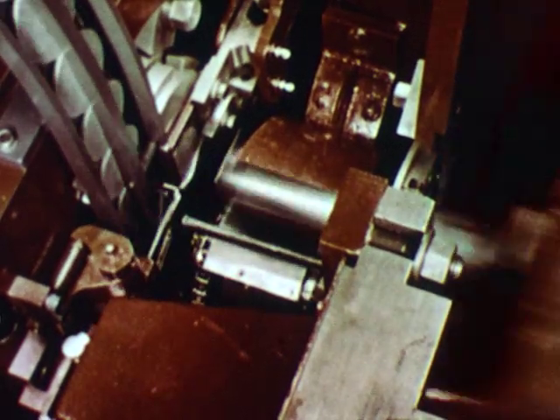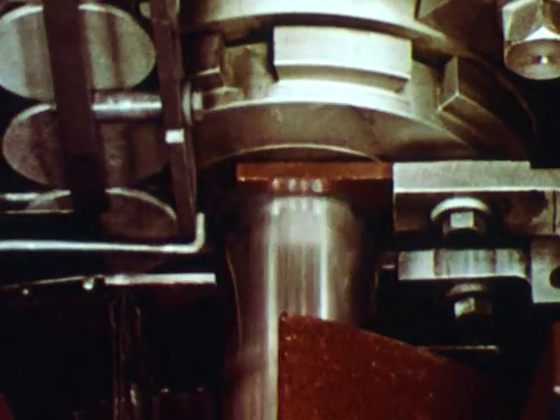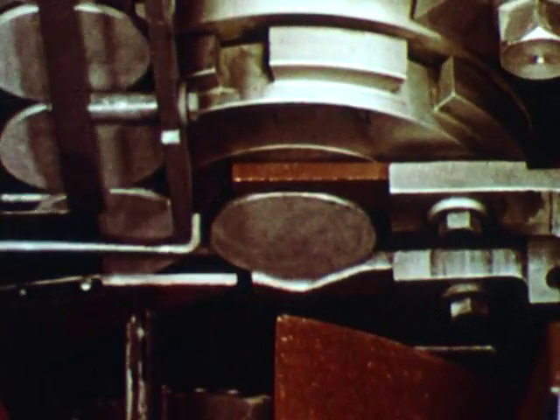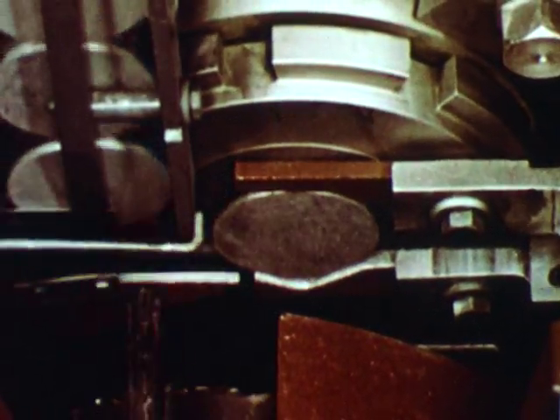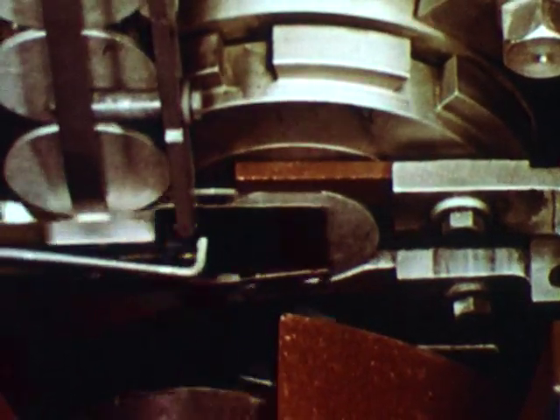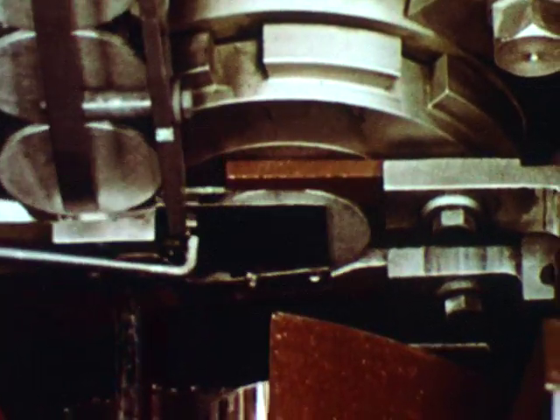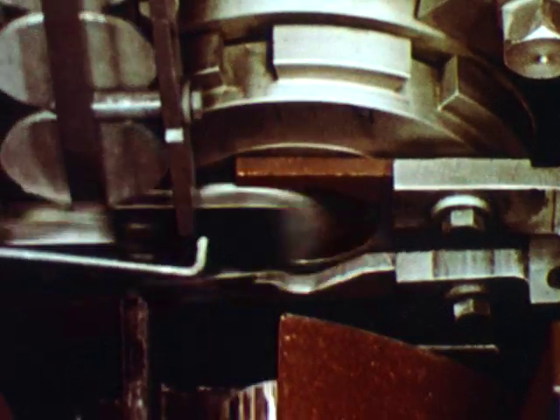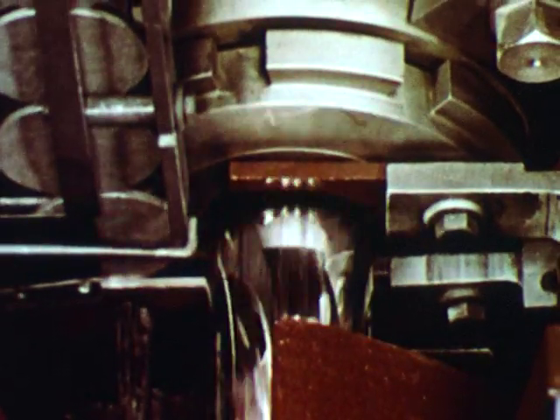The commercially pure aluminum blanks are 1/8 inch thick and 2.5 inches in diameter. In operation, the blanks are fed across in front of the die, where the punch carries them into the die for the backward extrusion. When the punch retracts, the cans are automatically stripped from the punch.